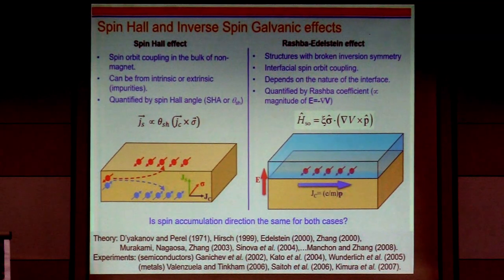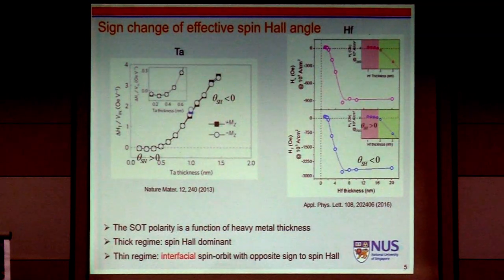So the easiest way is always to change our film thickness. If you make your film very thick, we assume it's bulk dominated. If you make it thinner and thinner, probably interface effects start to dominate. So in this graph, you can extrapolate the thick regime and the thin regime. The first measurement of this kind of experiment was reported by Masamichi Hayashi's group in Japan in 2013. In the case of tantalum, they changed the thickness from 2 nanometers down to very thin. Initially, everybody knows this material effectively has a negative spin Hall angle, and that's what they measured. But as they changed the thickness below 0.5 nanometer, they see a small but quite clear evidence of a change.